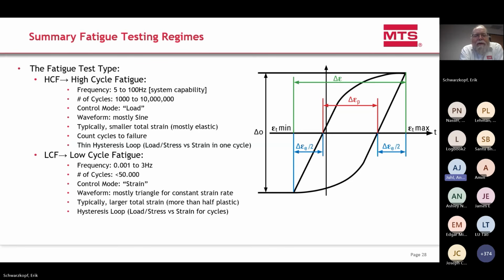It shows a green total strain, and it shows a red plastic strain. The plastic strain is the width of that hysteresis loop. In most HCF tests, the plastic strain is 0. In most LCF tests, the plastic strain is not 0, it is significant. Sometimes half of the entire total strain. In this case, the red region is half of the green region.